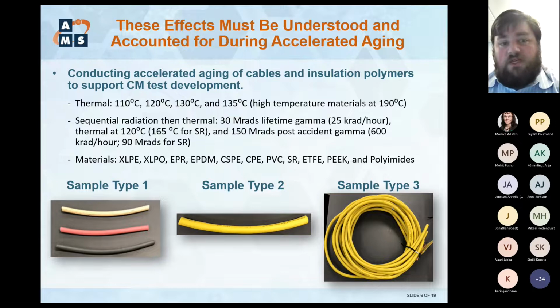And in the sequential radiation and thermal studies, what we will do is initially a radiation exposure at about 25 kilorad per hour, up to a lifetime dose of 30 megarads. So that's what we're actually using as our gamma lifetime dose, 30 megarads. And then we'll do a thermal exposure at 120C for the XLPE, EPR, XLPO materials. We're also doing silicone rubber in this program, and we do that aging thermally at 165 Celsius.